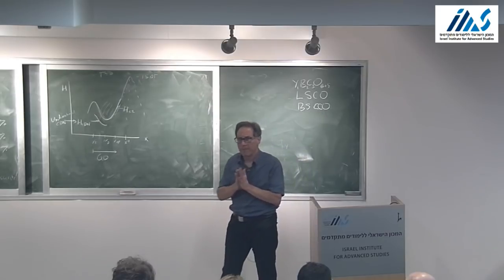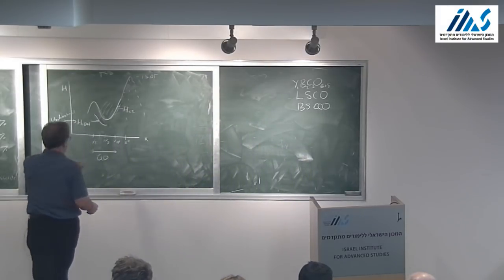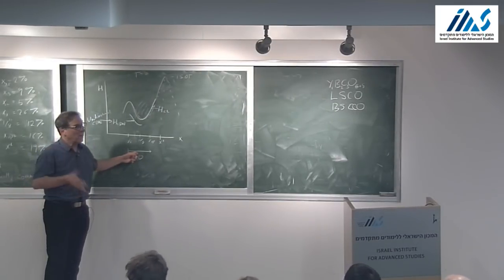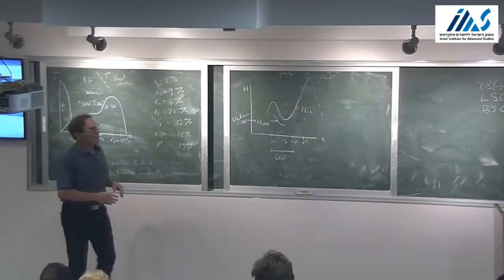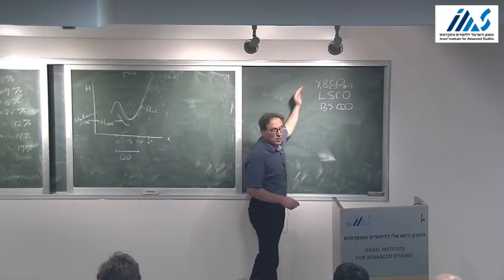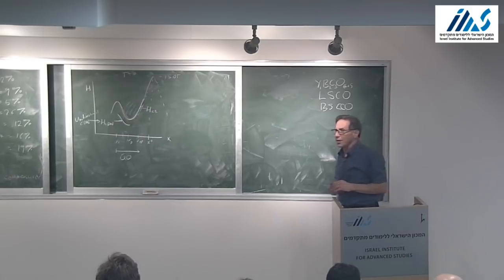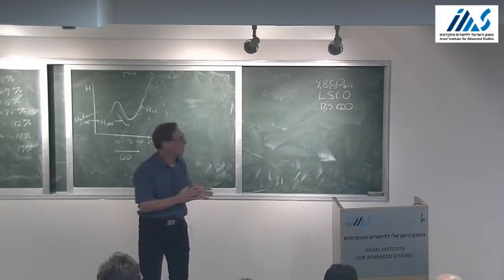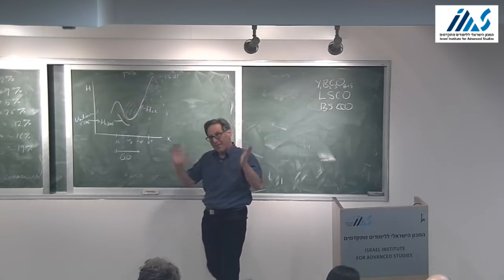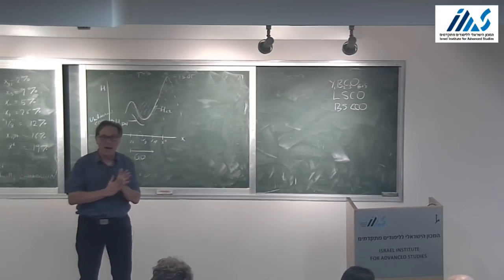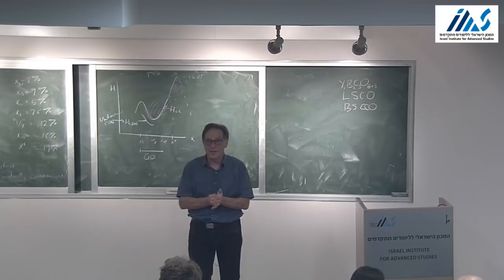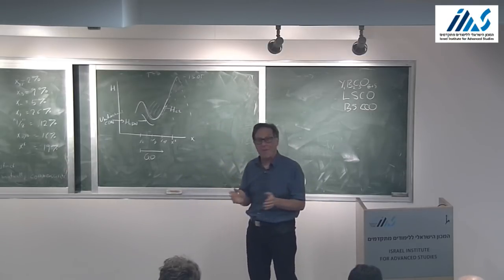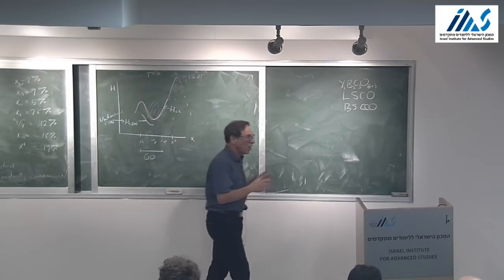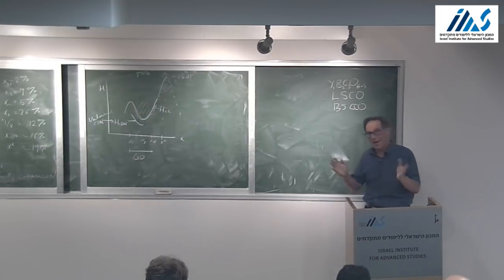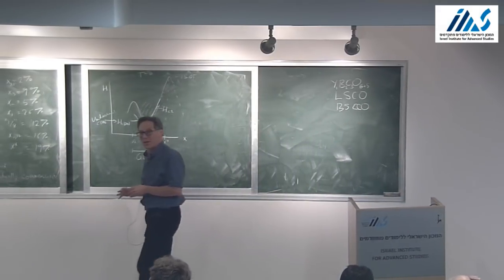Yeah? What about the Luttinger count? What? Yeah, so the Luttinger count for these quantum oscillations has nothing whatsoever to do with the Luttinger count here. Like ARPES, it is very difficult to do in YBCO, and in particular the doping concentration at the surface has nothing to do with the doping concentration in the bulk. In BSCCO, you can use the volume of the Fermi surface to make an estimate of the doping concentration, but the Fermi surface isn't very sharply defined. At low temperatures, it's pseudo-gapped. At high temperatures, the features are very broad. So you can get some estimate of the doping, but I wouldn't take it. I mean, any of these things involves some uncertainty.